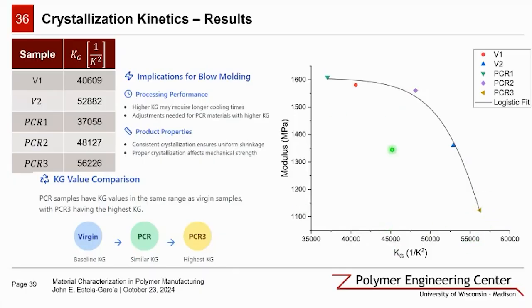And this is, again, likely due to the presence of contaminants that's disrupting the normal HDPE crystallization process. This unique behavior of PCR3 highlights those challenges of incorporating recycled materials with potential contaminations into our processes. Its higher nucleation energy barrier and the disrupted crystallization lead to an altered material structure and inferior mechanical properties. So these results underscore the importance of careful material selection and process optimization when we're incorporating recycled HDPE.